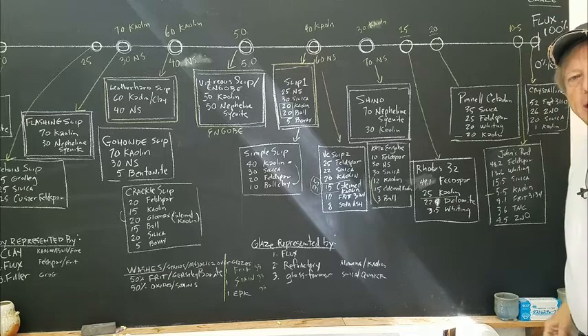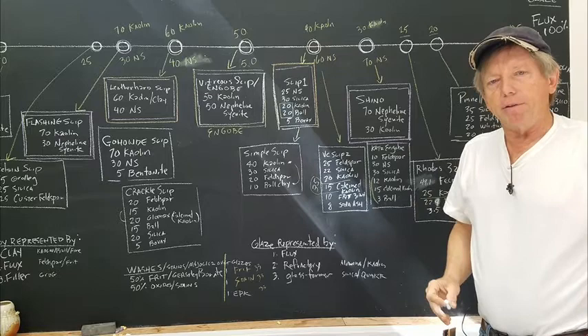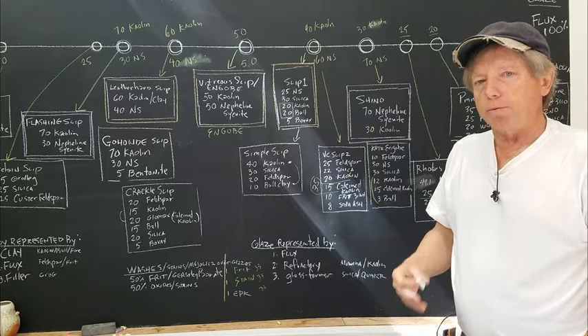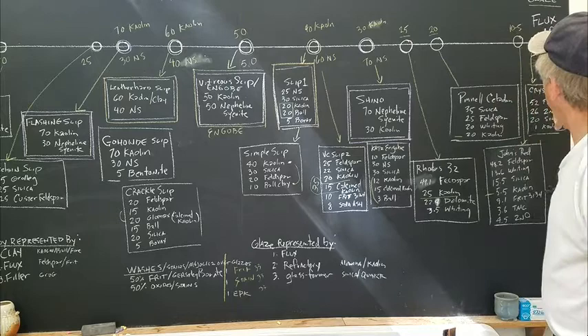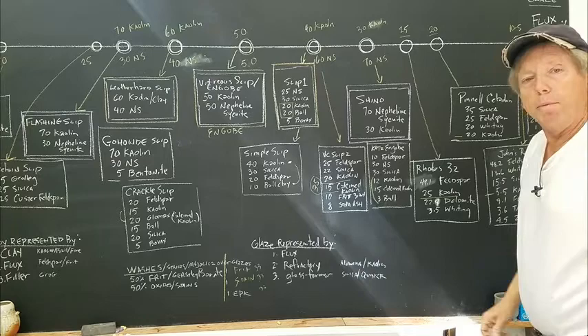These are like 5% kaolin, maybe 5 to 10, maybe even less. But they want less alumina in the glaze. It makes it brighter. The more alumina you have in the glaze, the more dull the glaze can become. So copper reds want to be very bright, so they'll be low alumina glazes. And then the final one here with almost no kaolin or alumina is crystalline glazes. Typically it might have 1% in there.